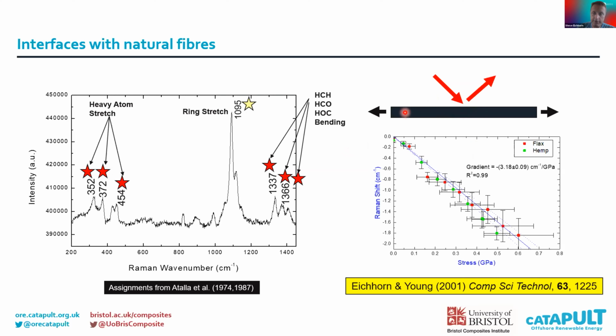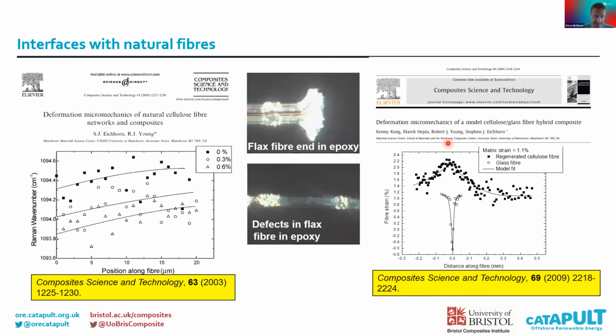Here we're able to measure what's called a Raman shift. So we take a fibre and deform it in tension, and then measure the position of a particular band in that spectrum, which corresponds to a stretching of the cellulose chains. Then we're able to do point-by-point mapping along the fibre once it's inside a composite, and that gives us the in situ stress state without having to take the composite apart. We can actually do it in situ. And we did this with a number of natural fibres.